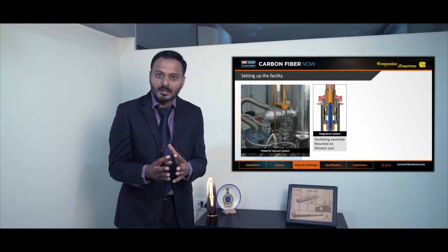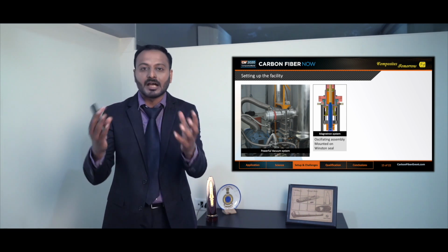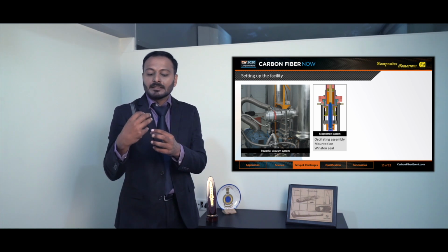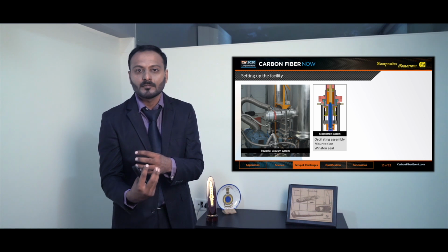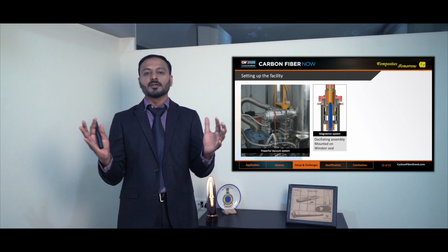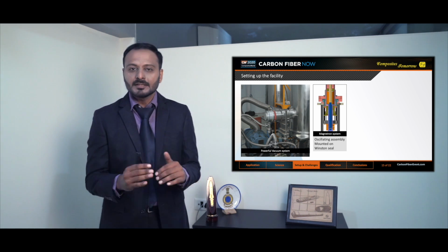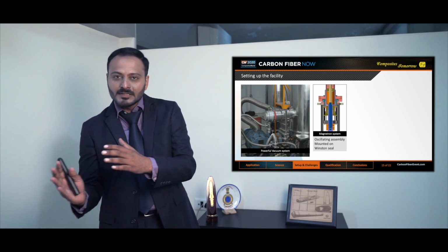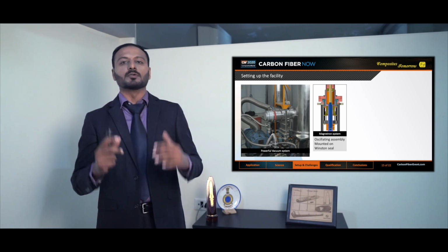Well, generally, due to the additional affinity or additional charge created by the magnetic field, the efficiency of reaction near the magnets would increase inadvertently, having a higher coating ratio near the magnets and the earth space is a bit left out. This is where we require the oscillation. This oscillation will spread the coating and have a more uniform outcome.